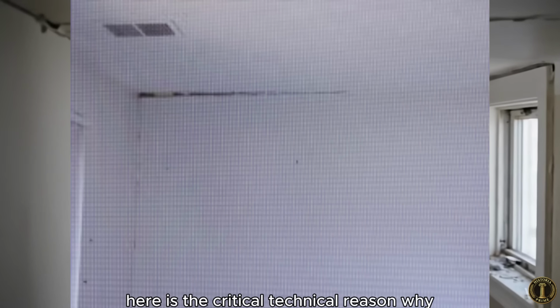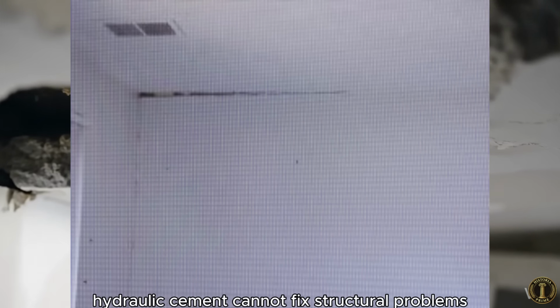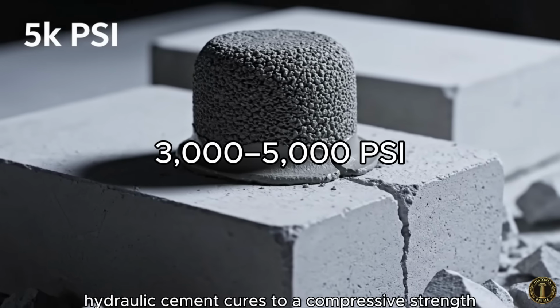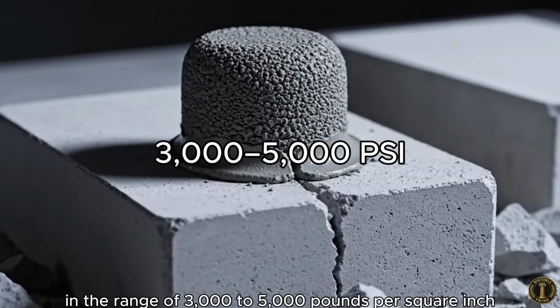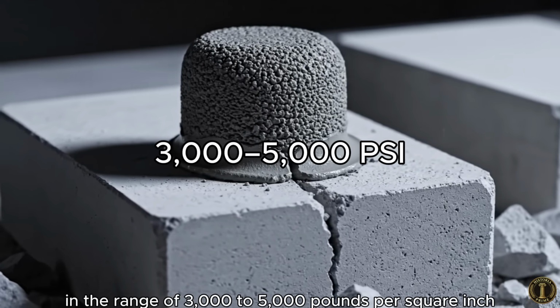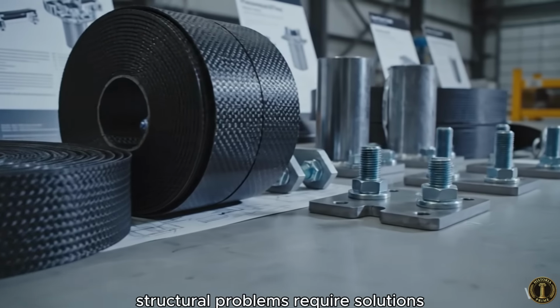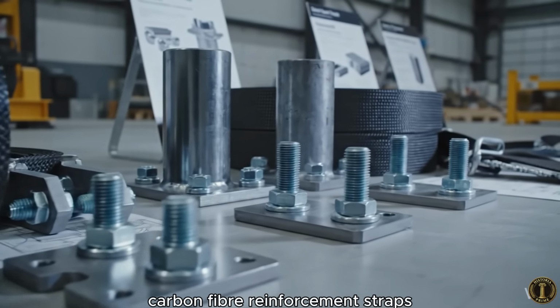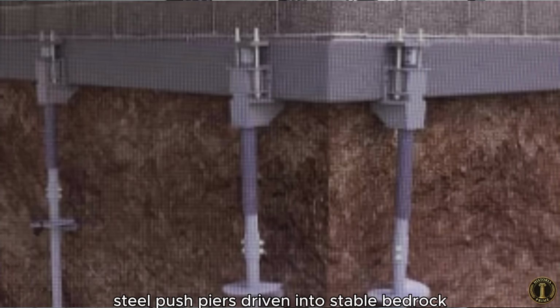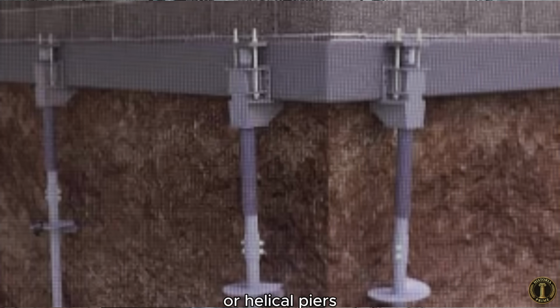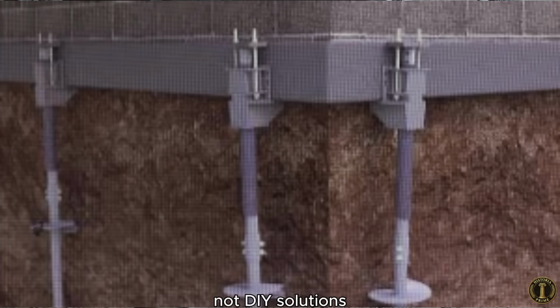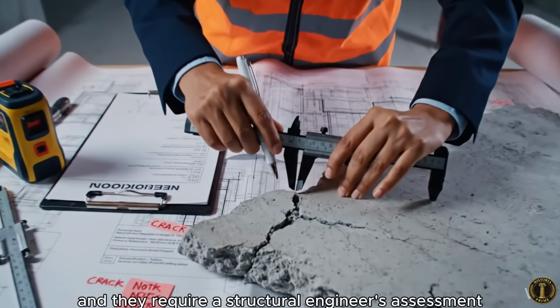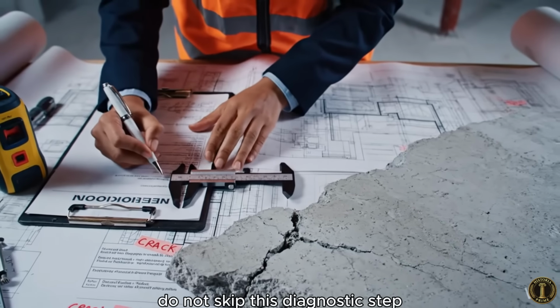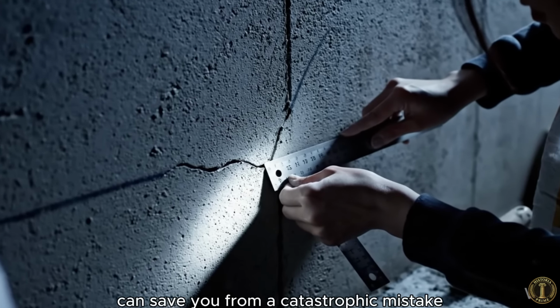Here is the critical technical reason why hydraulic cement cannot fix structural problems. Hydraulic cement cures to a compressive strength in the range of 3,000 to 5,000 pounds per square inch, depending on the product. That means it is extremely hard and completely rigid. If your foundation is actively shifting, this rigid patch will simply crack again. Structural problems require solutions that can accommodate movement. Carbon fiber reinforcement straps, steel push piers driven into stable bedrock, or helical piers. These are engineering solutions, not DIY solutions, and they require a structural engineer's assessment. Do not skip this diagnostic step. 5 minutes of careful observation can save you from a catastrophic mistake.